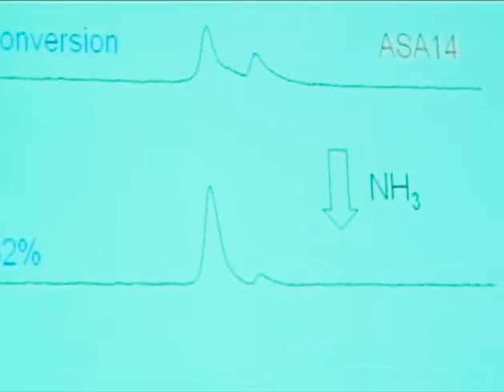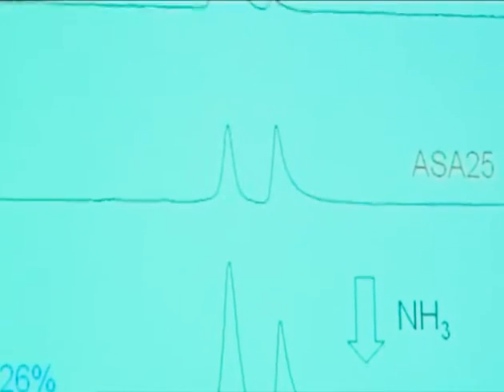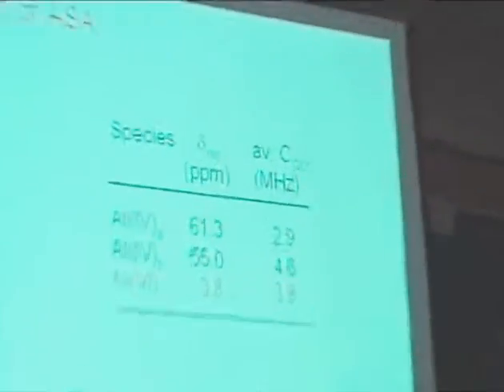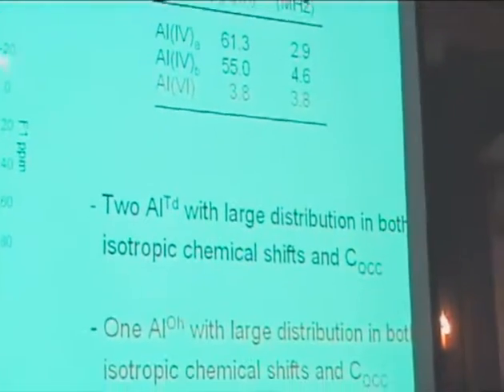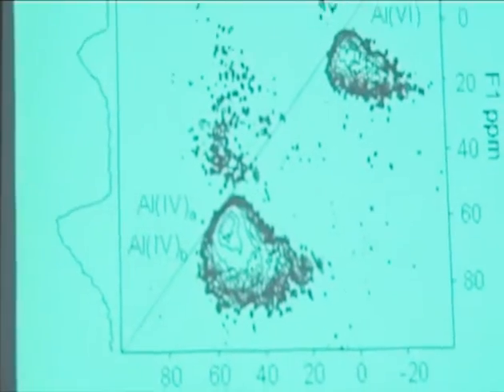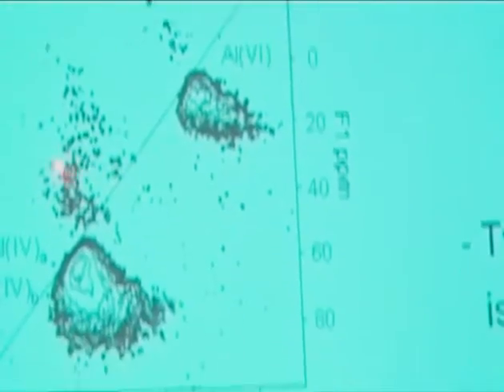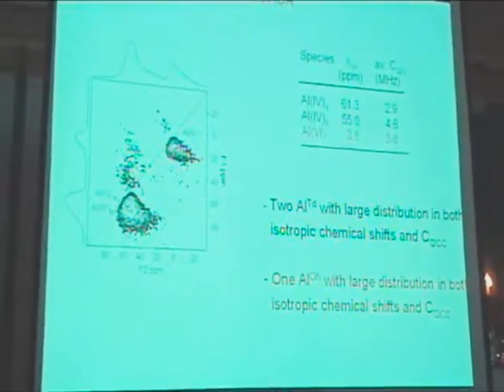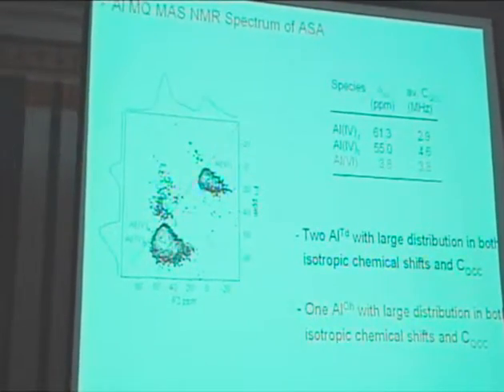Of course, when you go up in the aluminium content, then you introduce too much aluminium. It cannot be taken up, apparently, in aluminium tetrahedral positions, in zeolitic type of positions, be it amorphous, in the silica. And yes, indeed, then the ammonia trick does bring it down, but not completely. And indeed, now it's a real octahedral. So these are gamma alumina domains, or eta alumina domains, if you will. And you can look at it with two-dimensional NMR. This is a spectrum which we measured with a 700 megahertz machine that we, together with a few colleagues, recently got. And then you do it in 2 dimensions, like you do in organic chemistry, and you can distinguish between tetrahedral, and also the so-called pentagonal peak can be analyzed, and you can try to find out if that belongs to really tetrahedral or really octahedral, or if it's really pentagonal. So these kinds of studies in combination with XANES are very important.